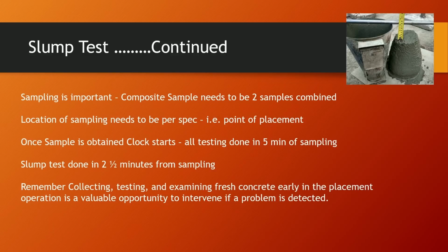All right, continuing on slump. Sampling is very important. A composite sample needs to be done with 2 different samples combined. Location of the sampling needs to be per spec. So again, we mentioned this, but look at your specifications. Typically, it's point of placement. Once the sample is obtained, the clock starts, and all of the slump test has to be done within 5 minutes of sampling. The slump test is done in 2.5 minutes from sampling.